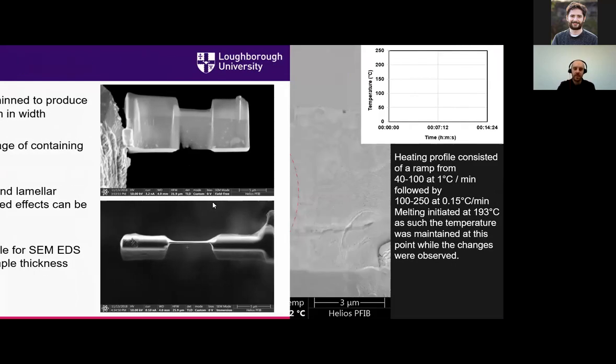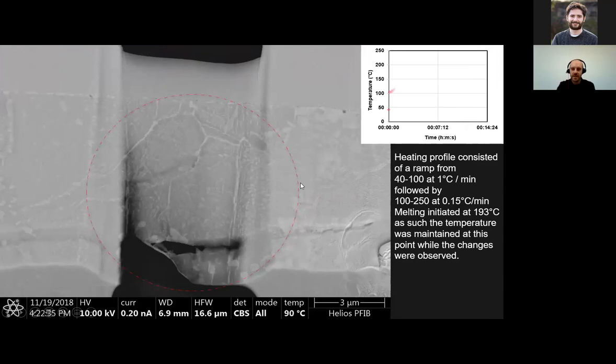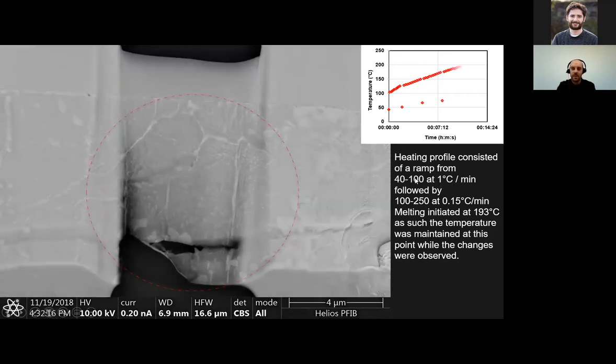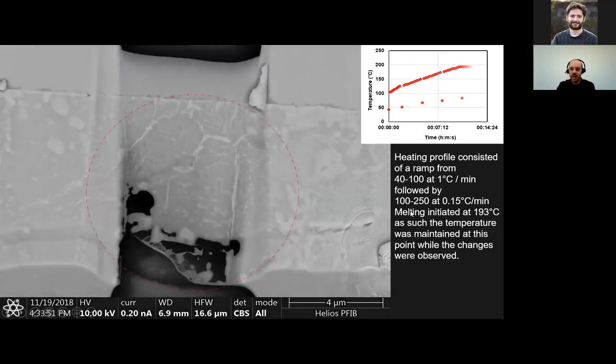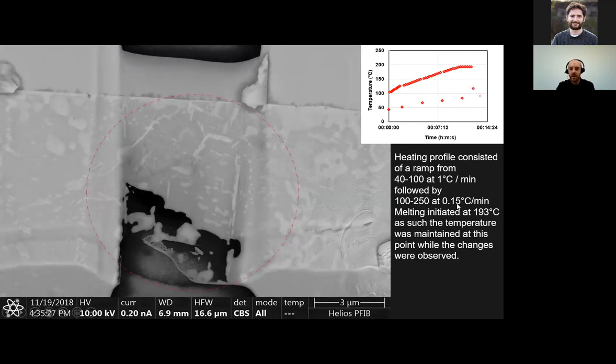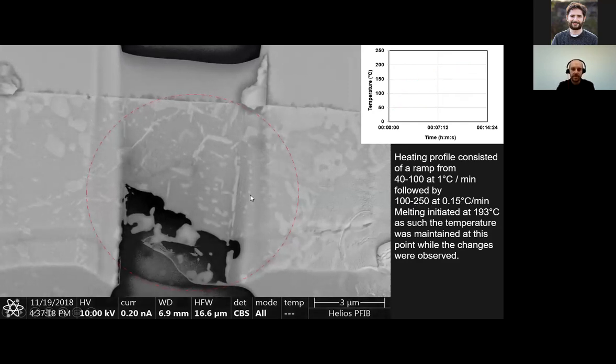So we'll move on. Here's our first attempt at heating the sample. You can see the red circle is what we would be able to see if we were in the TEM, but in this case we were in the FIB. We're heating the sample nice and slowly at 1 degree a minute, from 40 degrees to 100 degrees. And then once we get to 100 degrees, we're heating much slower at 0.15 degrees per minute.